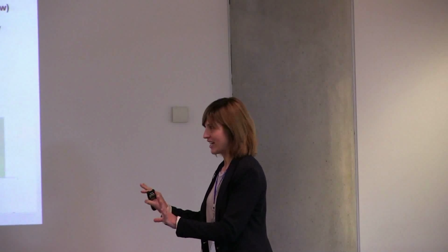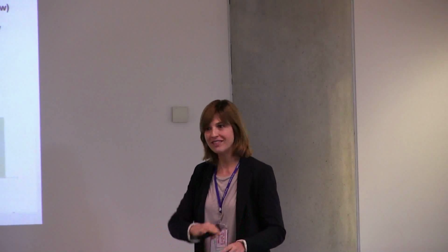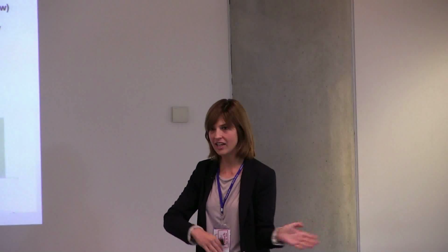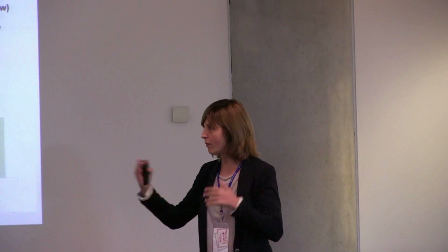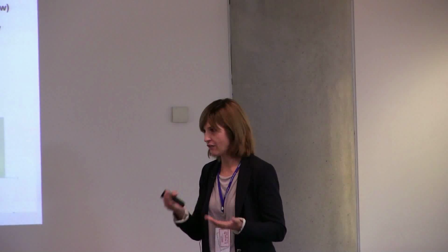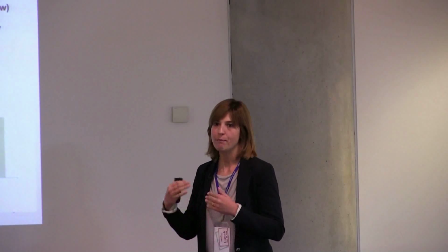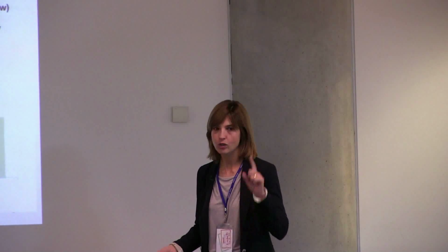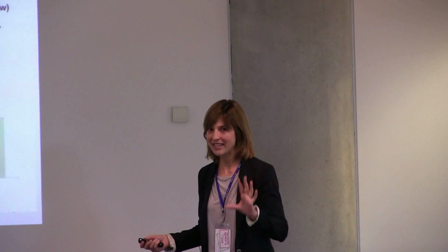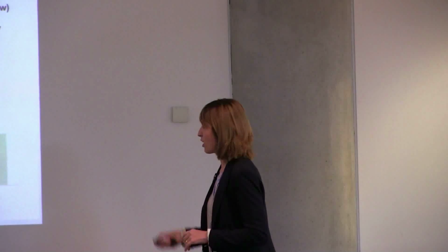And then finally, we didn't detect any difference in the digestion of the different nanoemulsions, with pectin, without pectin, with more or less surfactant. Okay? But the bioaccessibility was increased in those prepared with 2% of pectin. So the pectin can protect our compound during the digestion process.